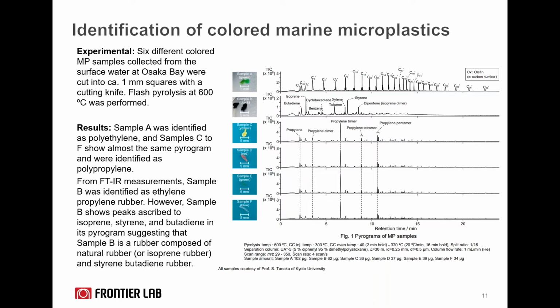But when it comes to sample B, from our FTIR measurement, sample B was identified as an ethylene propylene type polymer. However, sample B also shows peaks ascribed to isoprene, styrene, and butadiene in its pyrogram from the Pyrolysis-GC. So this more detailed information suggested that sample B is composed of both a natural rubber and a styrene butadiene copolymer.